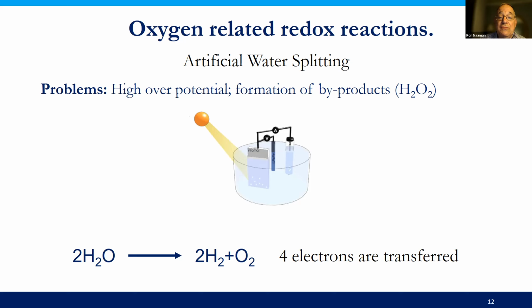And I don't want to go into too many details about the molecule, but what is clear here is that we have a strange situation. We start with water, which is singlet, and we end up with oxygen, which is triplet. So this reaction is in principle spin forbidden. So the question is how it occurs, and sure enough, when we do the artificial water splitting, people face two problems. One is overpotential, namely you have to apply potential higher than the thermodynamic limit in order to make it go. And secondly, there is the formation of hydrogen peroxide byproduct. Interestingly, in nature, this doesn't exist. So what is the difference?